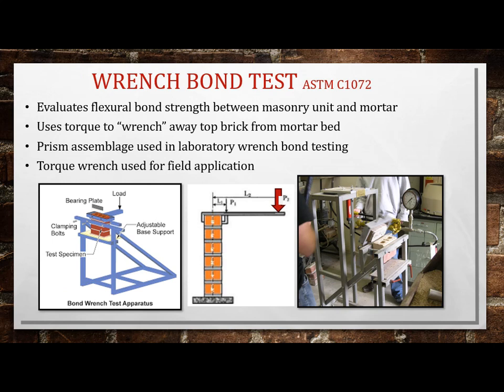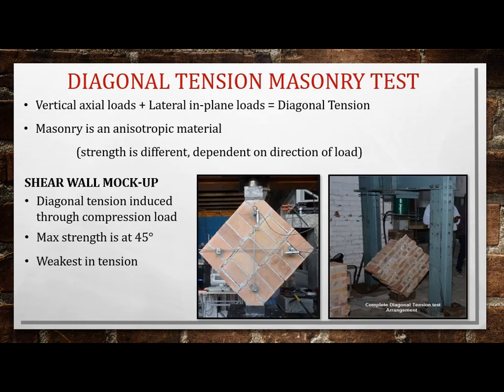Another test to determine the flexural strength of masonry, this is how a wall would perform under high wind conditions, is a wrench bond test. Again, the masons will make a prism. It's put in this fixture in a laboratory setting, and you measure the torque to wrench away, to tear off one brick from the brick below it. That force can determine the flexural strength of your mortar joint. You move it up, test the next one. You move it up, test the next one. There is a torque wrench application for the field that I'll show on a slide later.